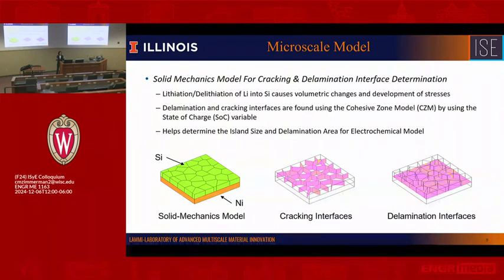First of all, we use the solid mechanics model to quantify the size of the silicon islands, and how the silicon islands change with the design of the electrode, including the architecture, the thickness, and also the microstructure within the silicon layer. After we get that information, we can pass that to our electrochemistry model. In this case, for the solid mechanics model, we have one thin layer of silicon deposited on nickel. In order to allow the simulation of the cracking and the delamination, which is the detachment of the silicon layer from the nickel base, we need a way for that cracking to be simulated in finite element.